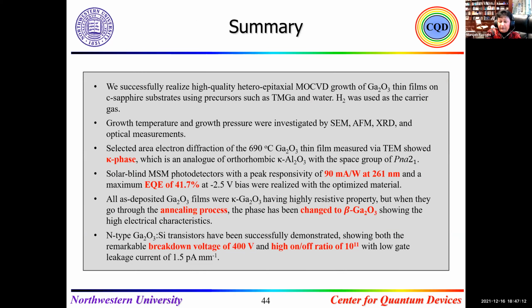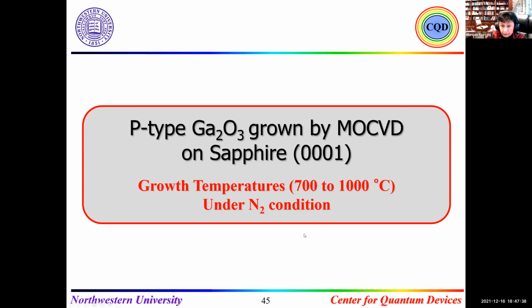So first of all, we demonstrated that yes, we can grow with hydrogen as a carrier gas and trimethyl gallium, and at the same time water, we can grow and get the kappa phase without any electrical resistivity. When we increase the temperature to 1000 for the annealing, it becomes beta phase and becomes conductive. That can give us transistors.